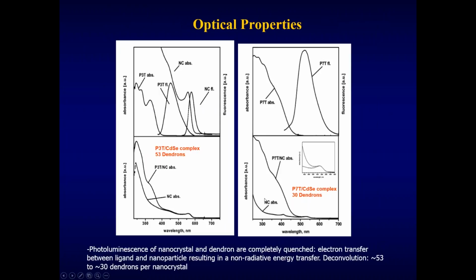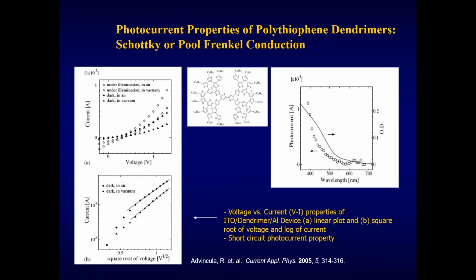So this cadmium selenide particle, through ligand exchange reaction, was then coated with the polythiophene dendrons. And we track this complexation or ligand exchange by FTIR. But from AFM, we were able to observe directly these hybrid nanomaterials individually as shown here, and the heights confirm the size of the nanoparticles to be about 4 nanometers, inclusive of the polythiophene ligand complex.